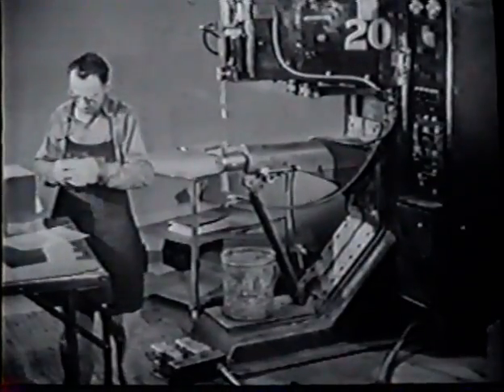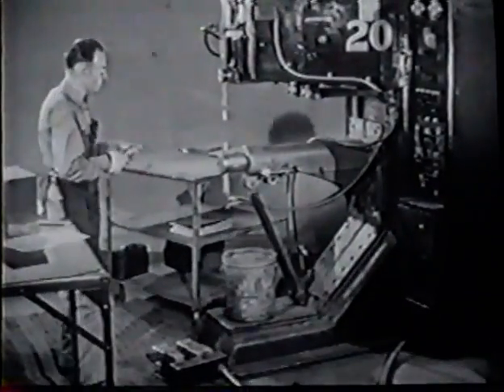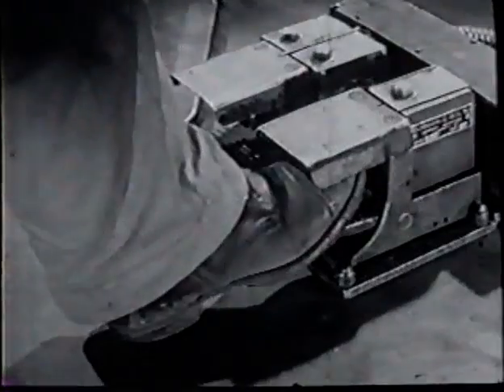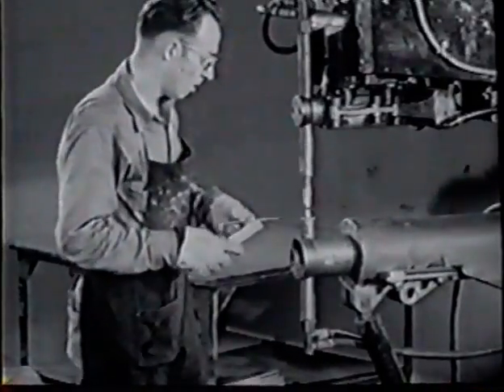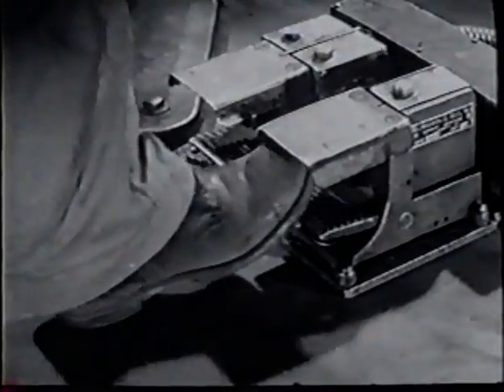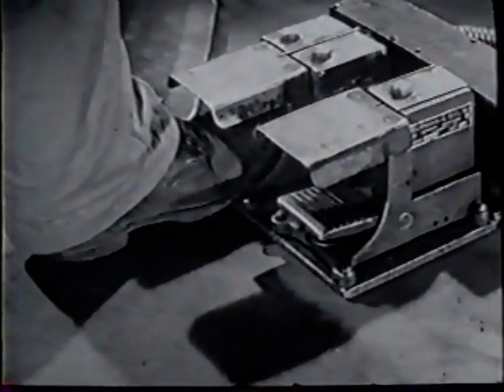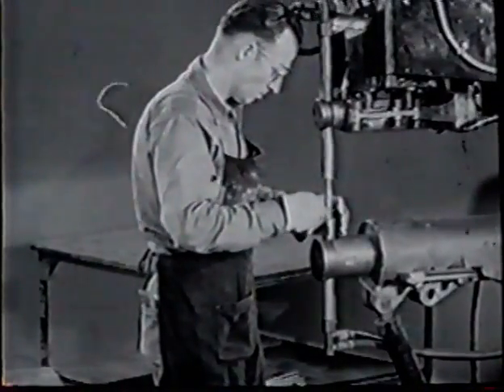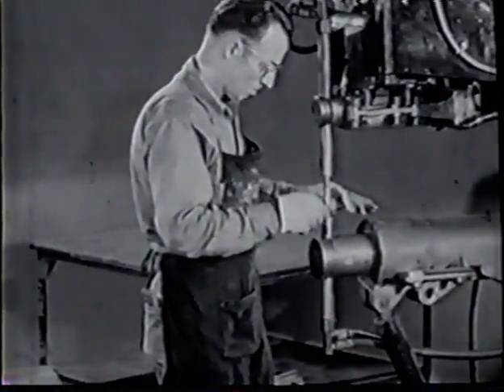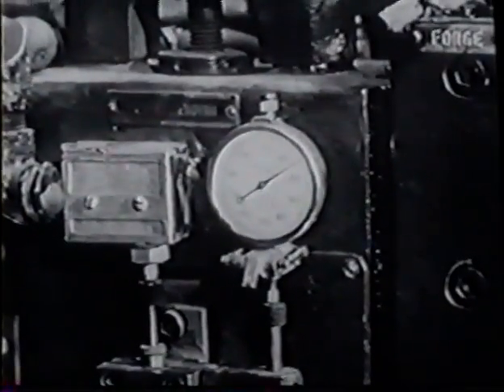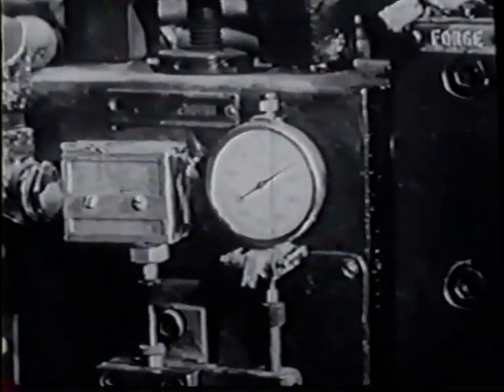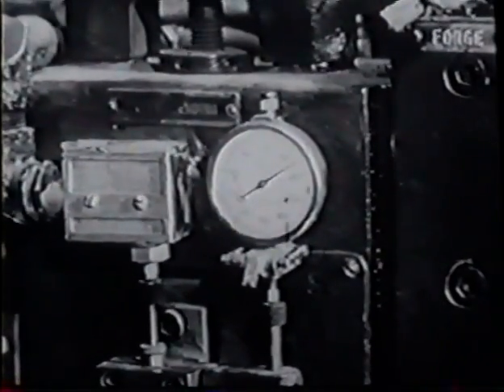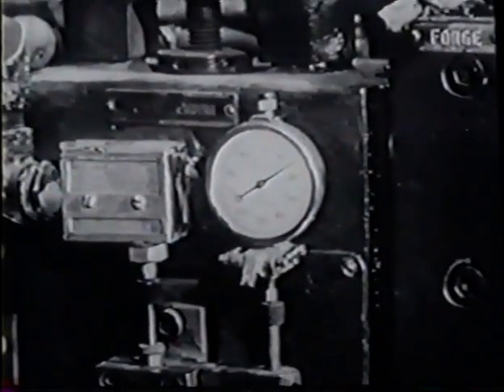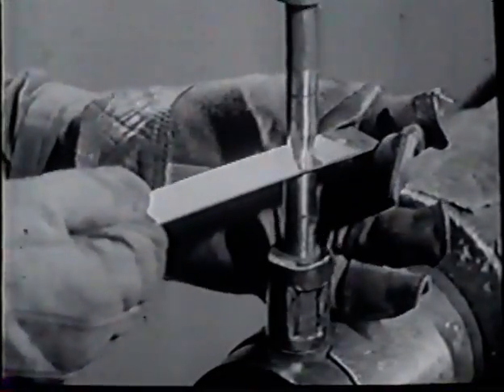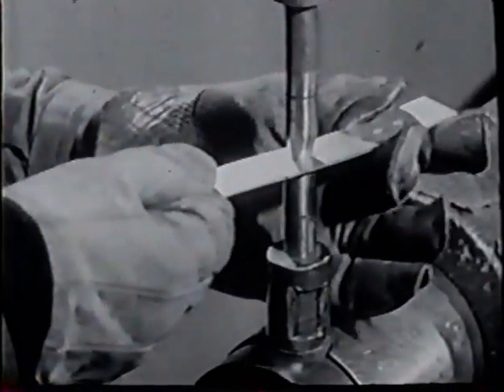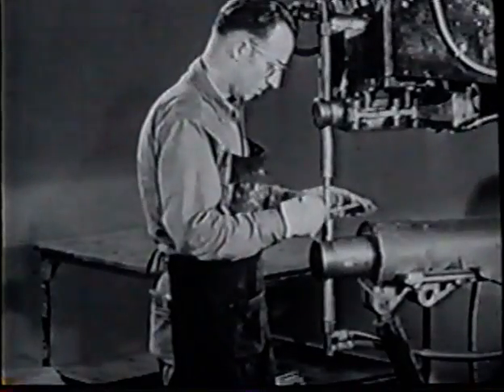Test the setup with sample strips of the same specifications as the production parts. Hold the strips tightly together and start welding. The machine fires under the conditions fixed by the control settings. Check the dial again to be sure you have correct weld and forge pressure. Your trial welds will be tested by the inspection department. If they meet specifications, your machine is ready for the production run.